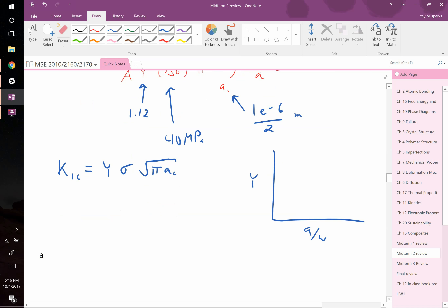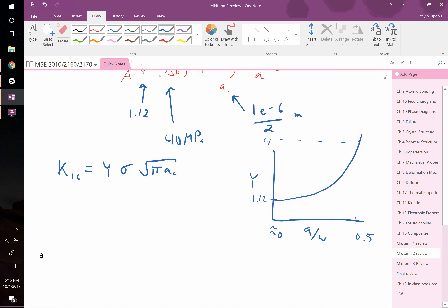Y looks like this: if you plot Y as a function of a/W — where W is how big your component is and a is the half crack length — if a/W is approximately zero, Y equals 1.12. But if a/W gets larger, reaching about 0.5, Y can reach around 4. If a/W is not very close to zero, you technically should not bring Y out of the integral. On this year's homework it made a noticeable difference.